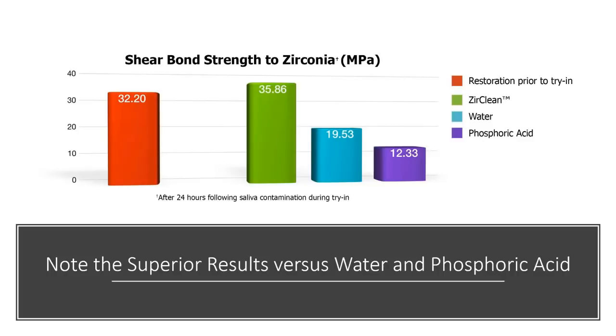Ivoclar has great studies with IvoClean cleaning their surfaces, and this is a Bisco study. It shows in red that when you try in a restoration, the initial strength is, let's say, 32 megapascals. With ZirClean, you actually increase the strength, in other words, the adhesiveness or the retention to the nanocrystal microstructure. But with water, look how much weaker it is. And with phosphoric acid, it's much, much weaker than the original strength. So this is why water, alcohol, and phosphoric acid are out. It's really IvoClean or ZirClean.